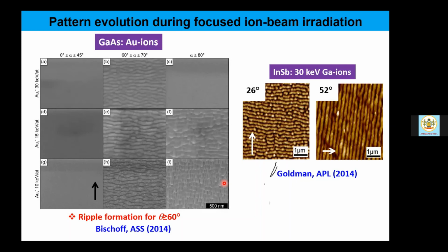Like that, you see indium antimonide using the broad beam, as I told, for both gallium arsenide and indium antimonide, spongy surfaces evolved. But for focused ion beam, where the incident beam dimension is squeezed up to a couple of tens of nanometers, these kinds of beautiful patterns evolved on indium antimonide surface. So there is a huge influence of the ion source, incident ions, and so on.